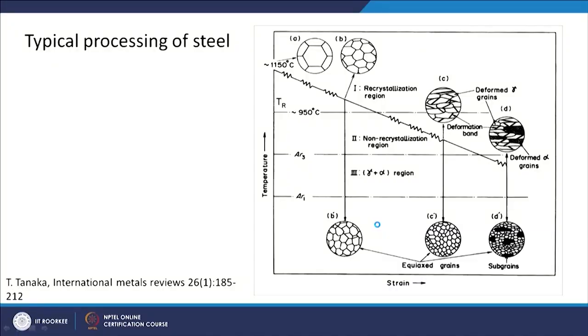Now, this is a typical processing of steel. And just to show you that when you do a processing in industry, what are the different stages of processing the material has to go through. So, as you can see the deformation or the material is starting somewhere from 1150 degrees Celsius. And these hatched regions here, these are the regions where you have imposed strain in the material. So, understand that these are all continuous processes. So, you heat the material and then it goes through the different stages of deformation.